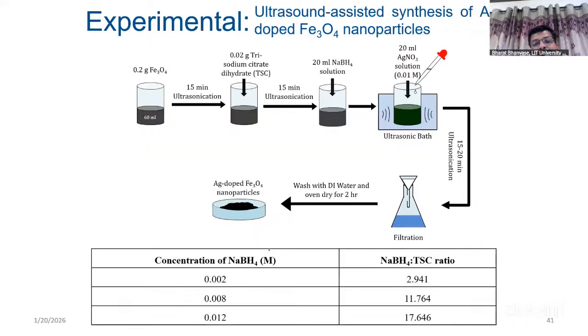So that was done in lab, and here we have taken some amount of Fe3O4, that is 0.2 gram, then it is sonicated for achieving proper dispersion. Then trisodium citrate dihydrate was added to stabilize the particle, and sodium borohydride was added, followed by dropwise addition of AgNO3 solution. This causes deposition of Ag nanoparticle on the Fe3O4 nanoparticle, and after filtration, you get Ag doped Fe3O4 nanoparticles.